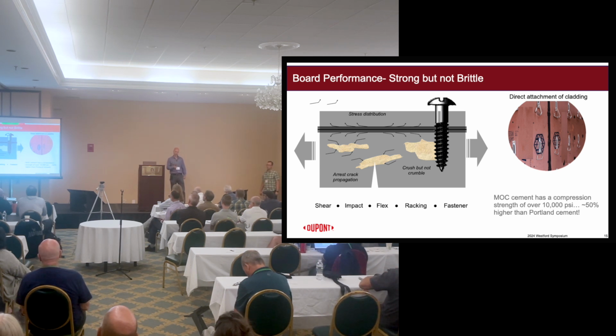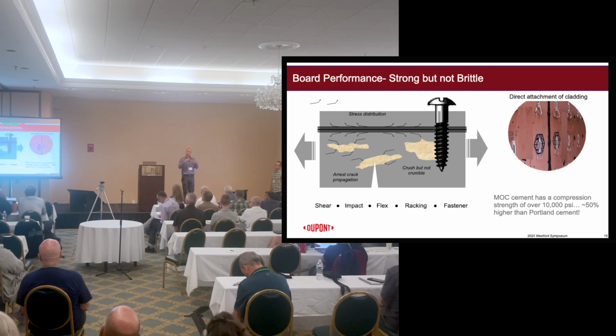MOC cement, I talked about that on the first slide. It is a very, very, very strong material. In fact, it's much stronger as a cement than Portland cement. So as we start to add these additives, wood, perlite, the overall strength of it starts to drop. But because we started so high, the final composite panel still has a lot of strength, but it also has toughness. So you can put a screw into it, it's not going to shatter, crack, and it's going to hold a significant amount of force.